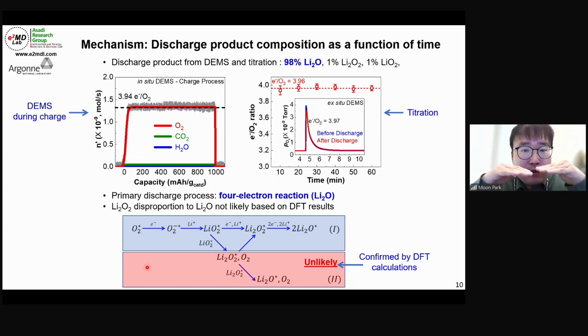So especially during charge of the battery, we charge the battery, and at the same time, we connect the DEMS at the end of the cell, and we measure the amount of oxygen evolved during charge. We use the known capacity, and by quantifying the amount of oxygen, we can get the transferred number of electrons during the reaction. The results from the in-situ DEMS showed 3.94 electrons, almost a 4-electron reaction. And also, ex-situ DEMS showed 3.97.